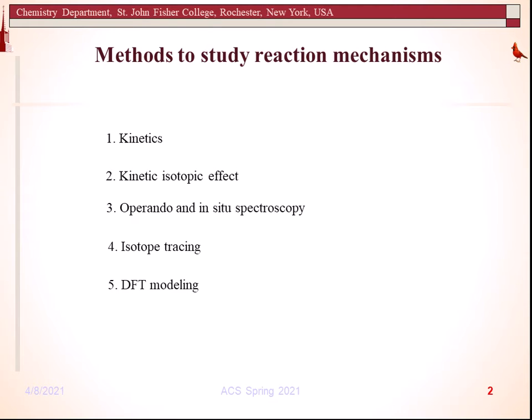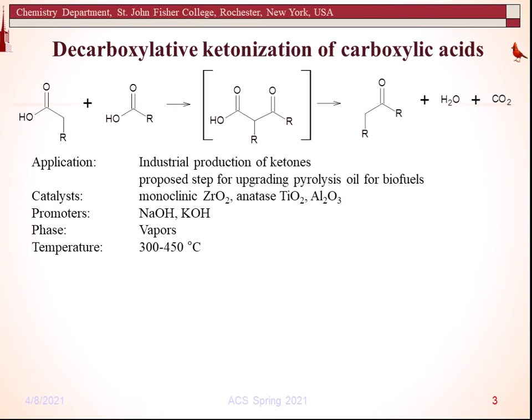One method remains rare, although a very powerful tool, and that is a study of reaction intermediates. It is rare because not all of the reaction intermediates are stable enough to be studied, and not all can be isolated by trapping or somehow else, especially on surfaces. If you suspect an intermediate, you could study its behavior separately and see what happens.